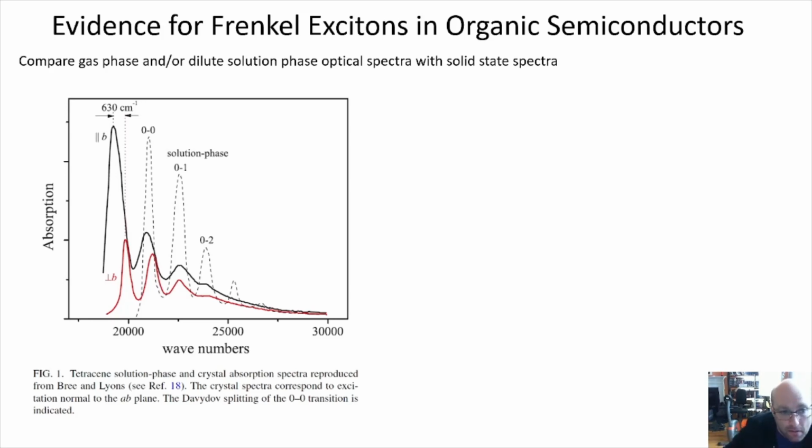by definition, its excited state properties are just those of a single molecule. And so if you then go and take that material into the solid state and the optical properties are not dramatically altered, then that's evidence that there is such a thing as a Frenkel exciton, namely an excited state in a solid that is predominantly localized on a single molecule or a single